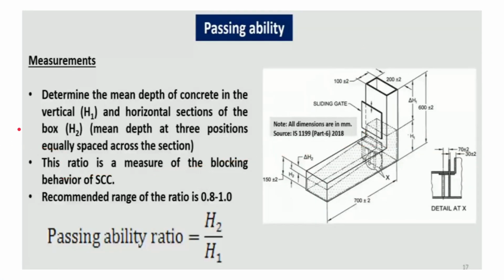So what are the measurements we take? We determine basically two measurements: the mean depth of concrete in the vertical section, h1, and the mean depth of concrete in the horizontal section of the box, h2. As you can see here, the h1 and h2 values are taken at three equally spaced positions across the section, to get a further mean value.